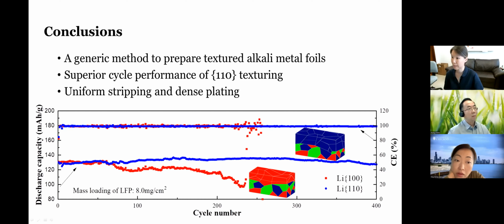Currently, we don't have the capacity. The reason is that all the samples are prepared by hand at the moment. So we do a pre-rolling, the scraping by hand, and then we do annealing. Annealing is generally fine. It doesn't matter how thin the foil is. But because you have to do this by hand, when the foil gets very thin, it is very easy to break.